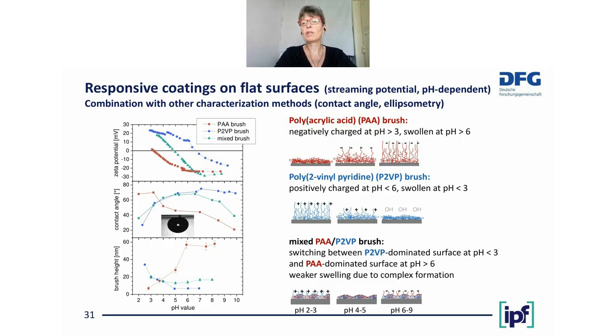And if we mix these 2 components, we get a so-called mixed brush. And this mixed brush changes its properties from those of poly-2-vinyl pyridine at low pH values when this P2VP is swollen to polyacrylic acid at high pH value when the polyacrylic acid is swollen. And you can see this very nicely in the zeta potential curves shown on top of the left graph. You can also see it in contact angle measurements, and you see the swelling in brush height measurements. But the zeta potential shows very nicely the switching from the P2VP properties to the PAA properties for the mixed brush.